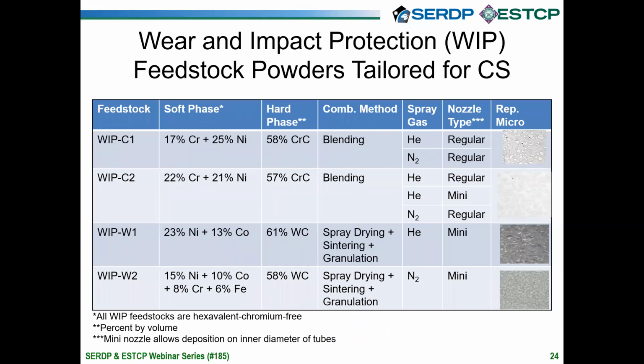So the outcome of that SERDP program was a series of cold sprayable feedstock powders that are tailored to wear and impact protection applications. And we call those powders the WIP powders for short. 4 powders were down selected for further evaluation on the ESTCP program. WIP C1 and WIP C2 are chrome carbide based powders, and they're produced using simple blending. And I do want to note that these powders contain chrome chemistry, but it's trivalent chrome instead of hexavalent chrome.